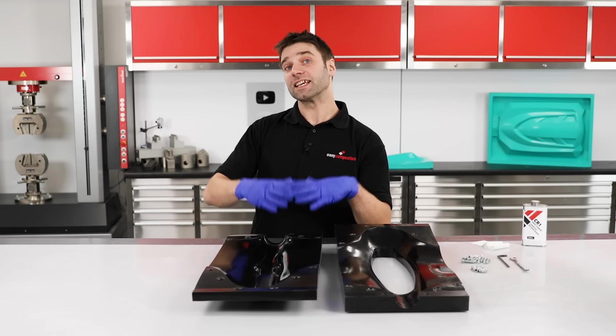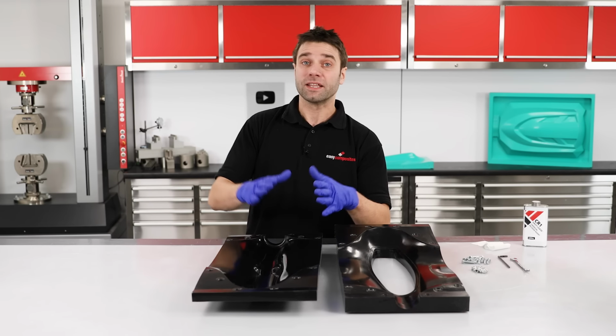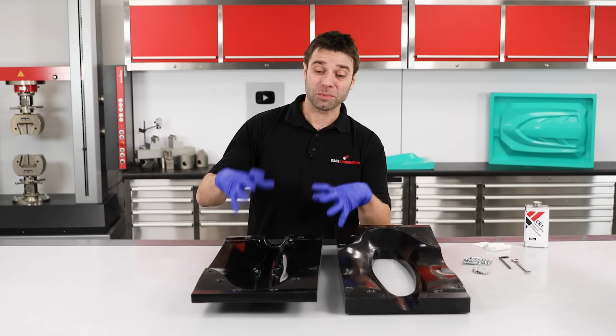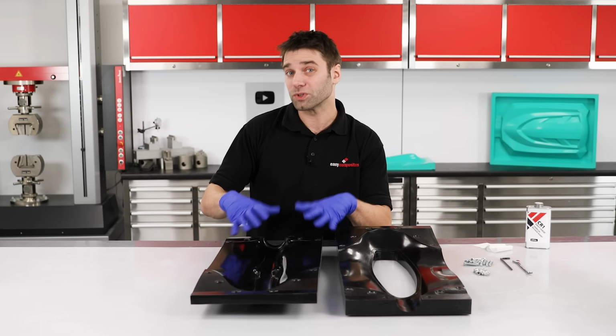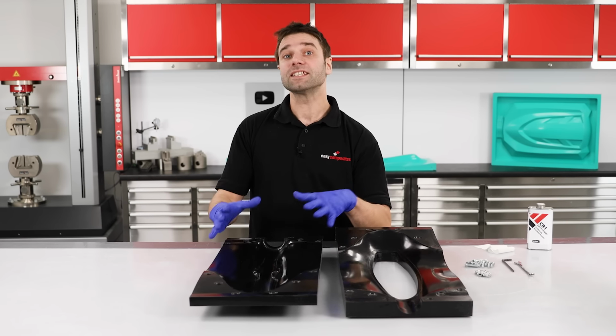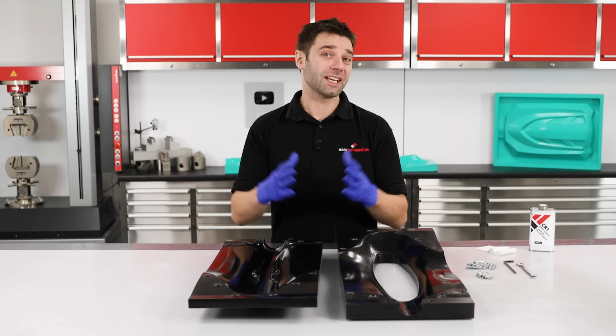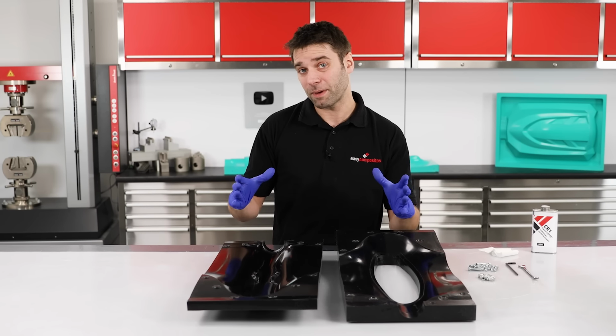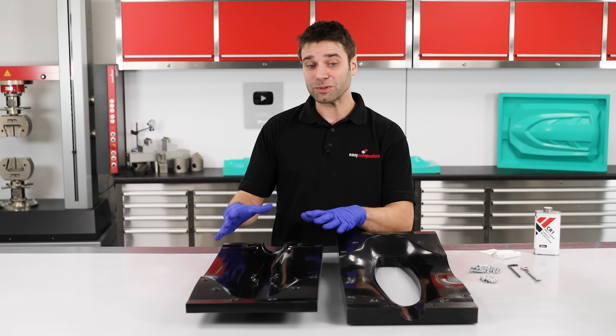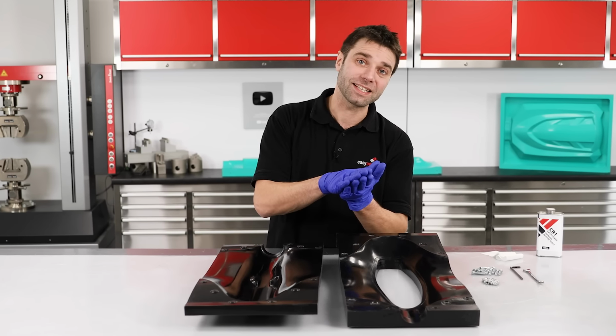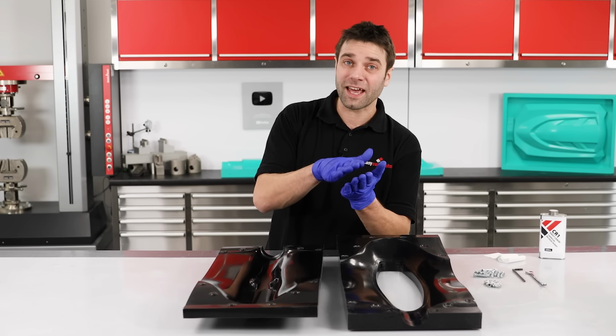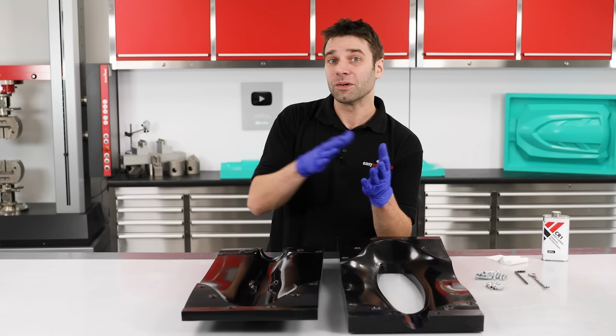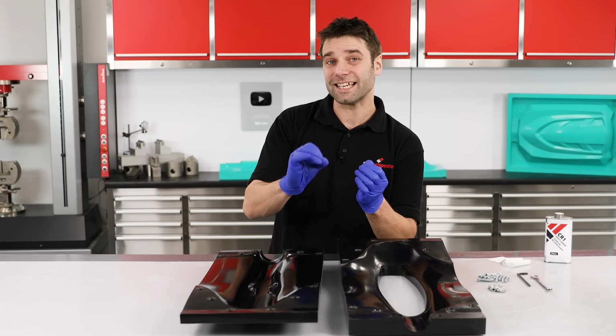The next step for these is to conduct what's known as a post-cure. This is an elevated cure cycle that goes up to the maximum service temperature of the moulds and fully cures them. This is done off the pattern as that eliminates any problems that you might have with thermal expansion. It also, in the case of split moulds, allows us to firmly clamp these together during the cure. In doing that, they're going to remain accurately aligned, which means once they're fully cured, they're going to sit together